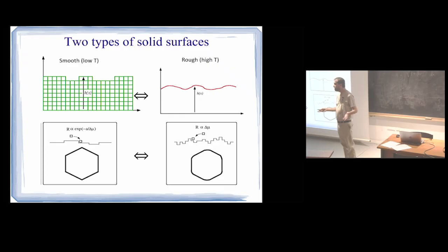And so we're used to seeing nice surfaces. When you increase the temperature, your vapor pressure is high, and then you have troubles making atomic resolution experiments, imaging of that. Okay? But at sufficiently high temperatures, or when the two phases are sufficiently alike, many times the solid surface is rough. There is no distinction in solid surfaces that are rough with an ordinary fluid interface. Okay? Of course, the viscosity is going to be much higher. But the static structure is not distinguished from that of a liquid-liquid interface when you are rough.